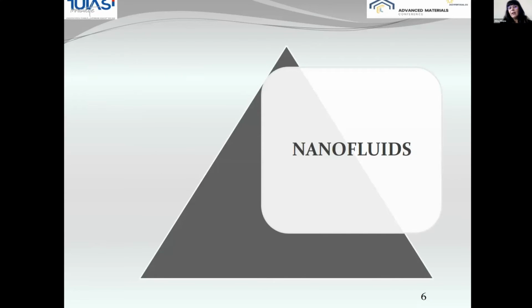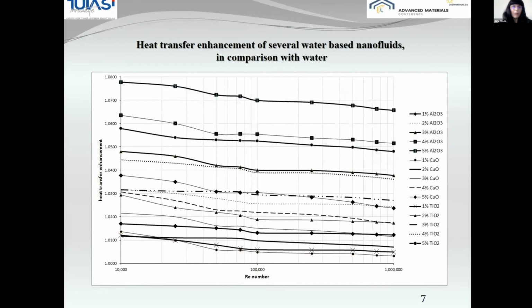So nanofluids, what we studied were based firstly on water. And as you can see also in this slide, we added some oxide nanoparticles, and you can see that the heat transfer enhancement was very good. We get up to 8% heat transfer enhancement compared with water at different Reynolds numbers, mostly investigated in turbulent convection.